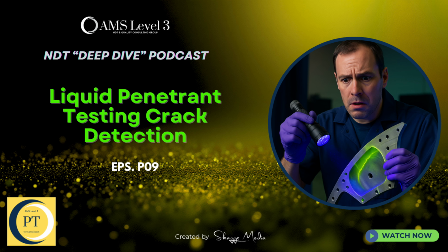And achieving that high contrast means you need pretty specific viewing conditions, right? Oh, absolutely. You must view it under black light, which is technically UVA radiation. And the inspection booths have strict requirements. You need a minimum UVA intensity hitting the part, typically 1,000 microwatts per square centimeter. That sounds like a lot. It's a good amount of UV, yeah. And at the same time, the ambient white light in the booth has to be kept really low, no more than 2 foot-candles.